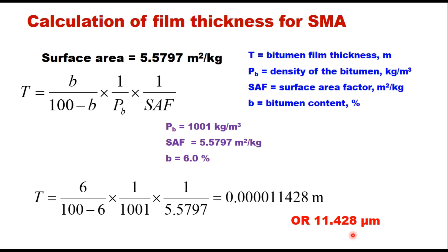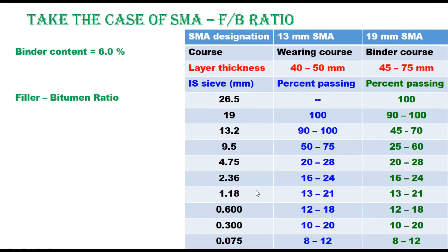This thickness is more than the thickness obtained in the BC-1 grading case, and this enhanced thickness provides more durability to SMA mixtures. Now if you calculate the filler-binder ratio for this mixture, with filler content 8 to 12% and binder content 6%, the filler-bitumen ratio can range from 1.33 to 2.0. This is why SMA is provided with higher binder content — the higher filler-bitumen ratio and higher binder content together impart more resistance to rutting in these mixes.